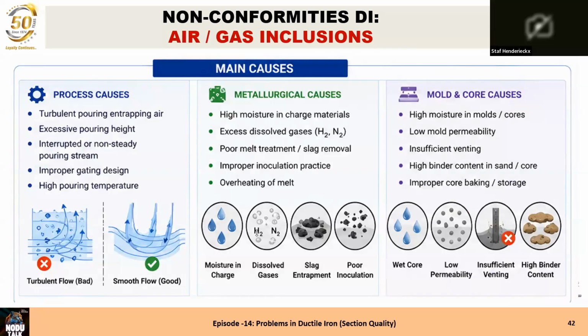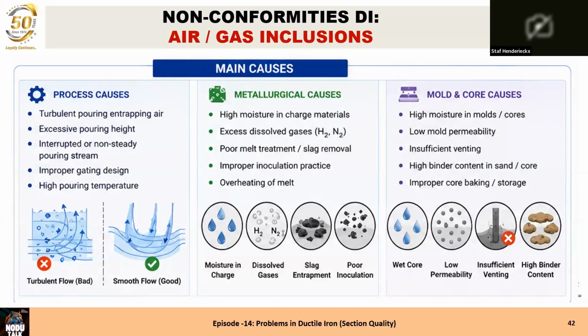Higher binder content in the sand and core means that if the coating is penetrated and the liquid metal touches it, if there is a lot of binder in it, you will have a lot of gas. If there is less binder, you will have less gas. And for improper core baking, you can have gas still coming when it's not baked properly.